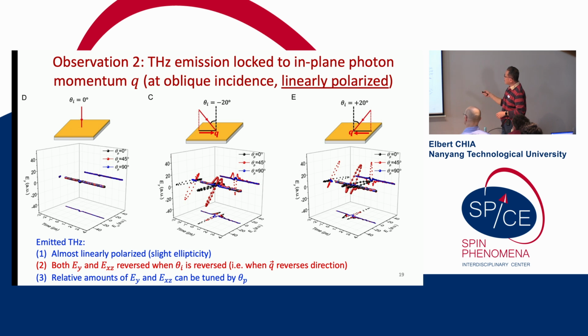We went ahead to adjust other knobs. So we use linearly polarized light, and we pump at minus 20 degrees as well as plus 20 degrees. So as you can see, going from minus 20 to 20, all that we change is the direction of the photon momentum. And you can see here for both the XZ component and the Y component of the emitted Terahertz pulse, there is a flip. It flips from here to here, and it flips from here to here. So both the EY and EXZ were reversed when theta I is reversed, and that is when the in-plane photon momentum Q reverses direction. So this is consistent with photon drag.